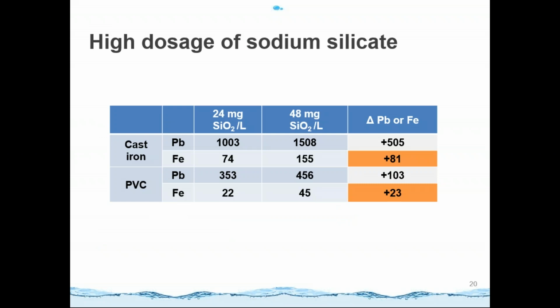The result is surprising, because when we increased the sodium silicate dosage, we observed an increase in lead and iron. As we can see from this table, for the cast iron supplied lead pipe, the increase in lead was 505 micrograms per liter. At the same time, we observed an increase in iron of 81 micrograms per liter. But for the PVC supplied lead pipes, the increase in lead and iron is relatively lower, which was 103 micrograms lead per liter and 23 micrograms iron per liter.